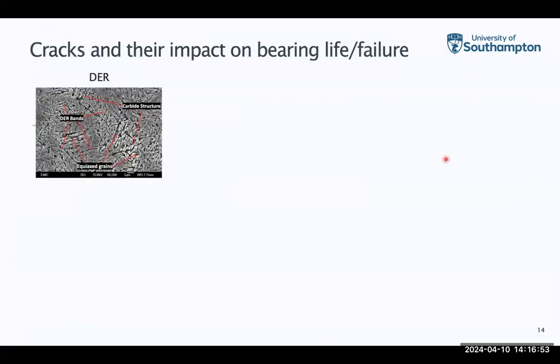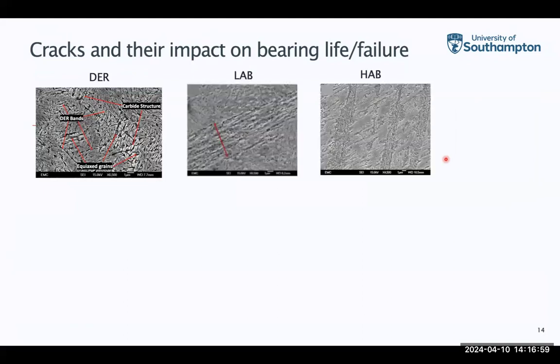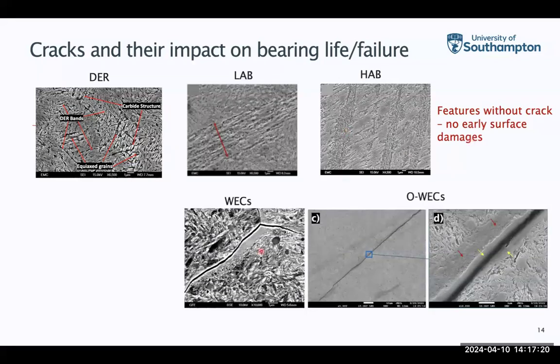Also, we looked at the influence of cracks in these features and their impact on bearing life. What we found is that features like the dark etching region, which has the small bands here, and also the low angle bands and the high angle bands here, don't have cracks. We did loads of detailed analysis and found that they don't have cracks, and they don't lead to early surface damages either. With the white-etching cracks and oriented white-etching cracks, we found they both have very obvious cracks in the structure, and both of them lead to early surface damages and even early bearing failures.